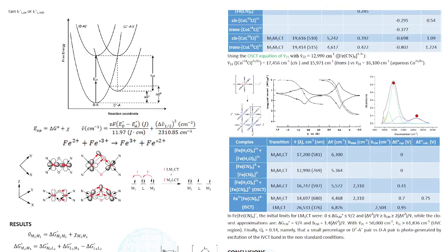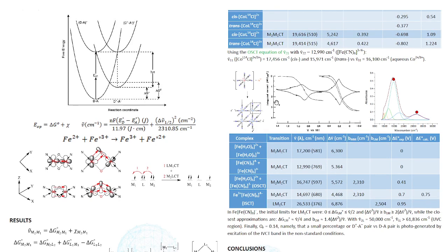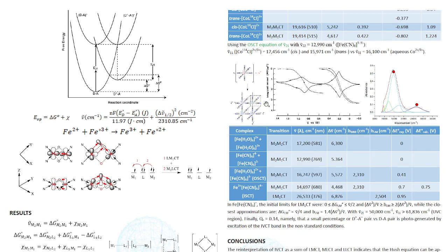The second case was interesting compared to the first one, using Prussian blue. In this case, the hexacyanoferrate complex reacts with iron chloride. It could be +2/+3. The potential difference suggests from the precursors that the donor is the iron chloride at 0.7 volts, whereas the acceptor will be the hexacyanoferrate at 0.33 volts, a reversible wave for each. Whereas in the bimetallic complex that makes an array, the donor and the acceptor roles reverse.